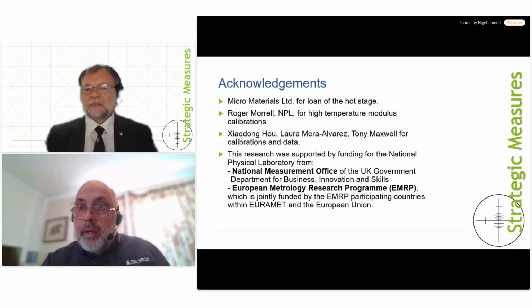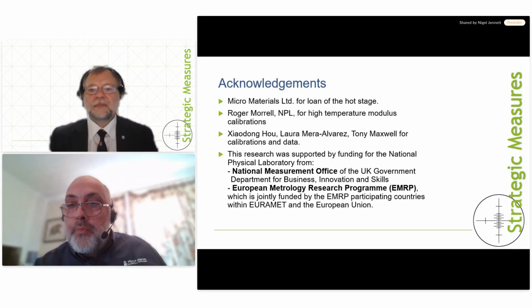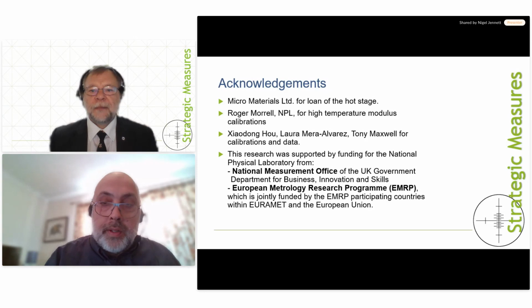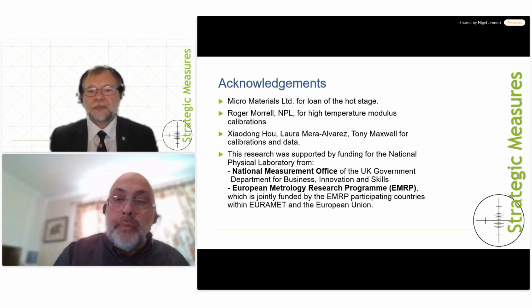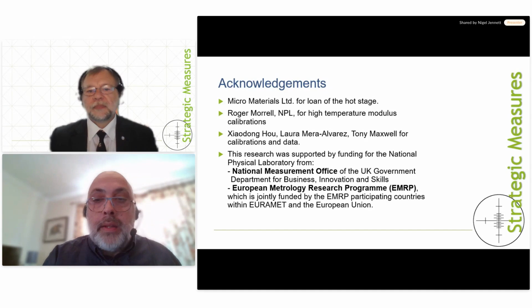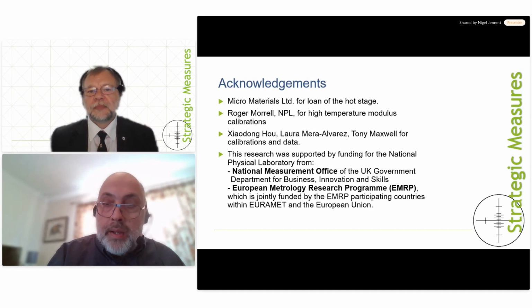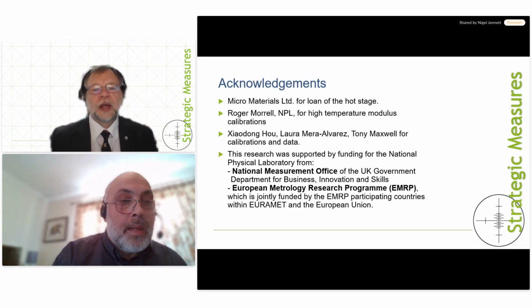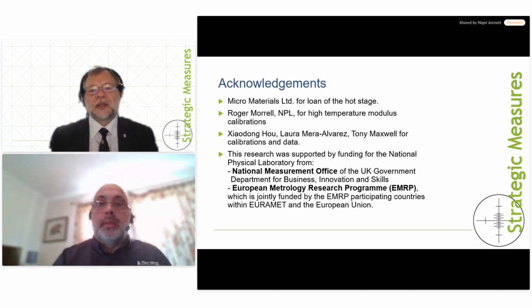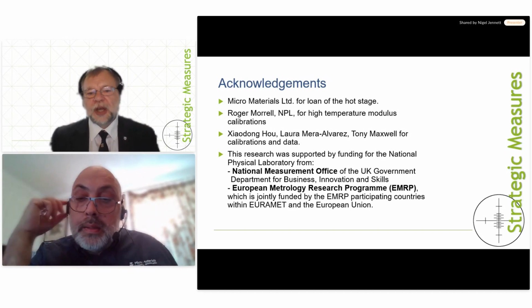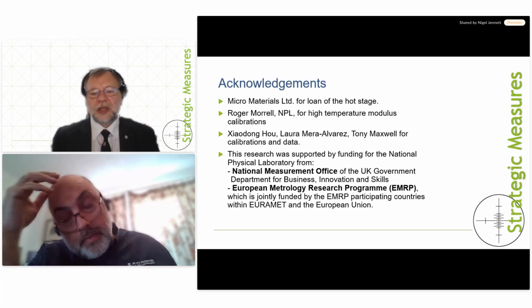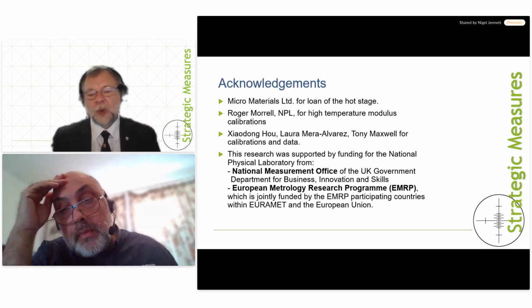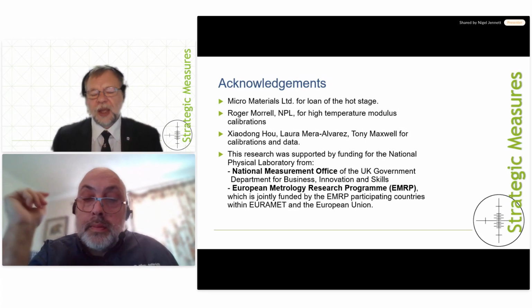From Andrew Bird. When assessing heat flow by bringing the indenter into contact with the sample, do you need to apply a sufficiently high load to allow heat to flow across by creating an appreciable contact area, rather than just resting the tip on the surface? Okay, that's a very good question. And clearly, if you increase the contact area, you can increase the heat flow into your indenter body, which is what you're using as a thermometer.